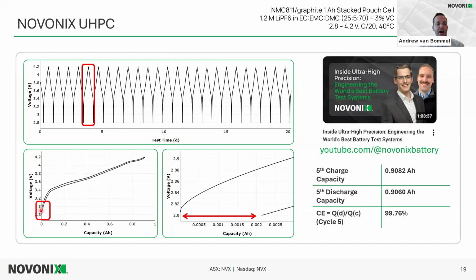When we look at cycle 5 and we have that charge and discharge, if we fold it over itself, at first it looks like that discharge is the same length as the charge, and we have 100% efficiency. If we zoom into this area, we see that it's not completely efficient, that there is a difference between the discharge and the charge. The fifth charge capacity is 0.9082 amp hour. The fifth discharge capacity is 0.9060 amp hour. And then that coulombic efficiency, the ratio of discharge to charge, is 99.76%, so not quite 100%. Herein lies where we need that accuracy and precision, where NOVONIX UHPC is helpful.